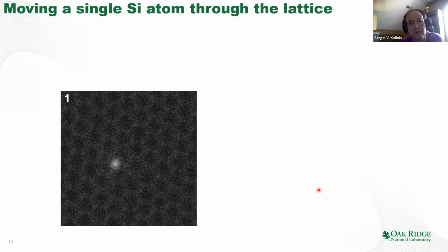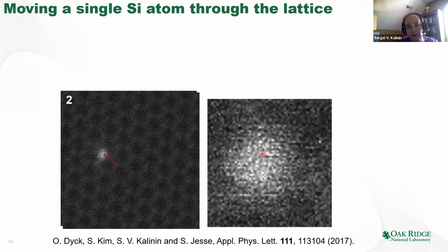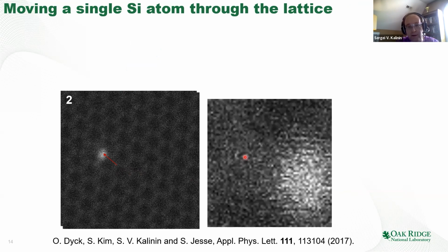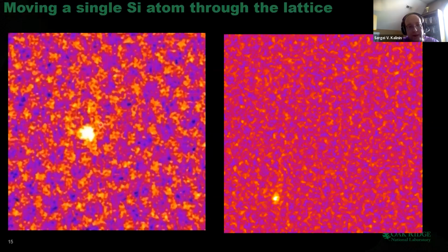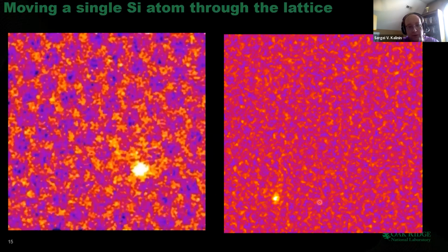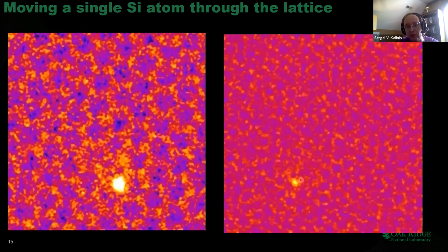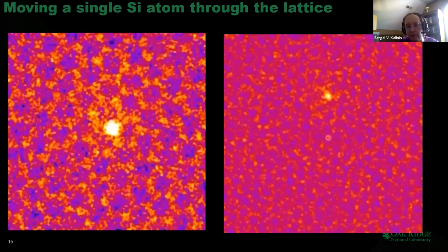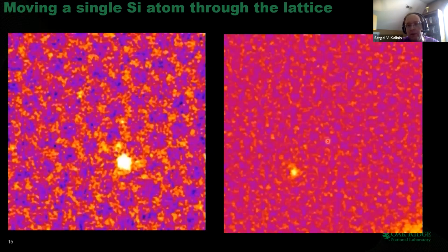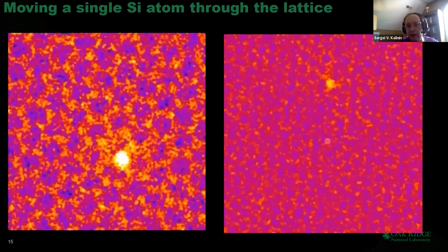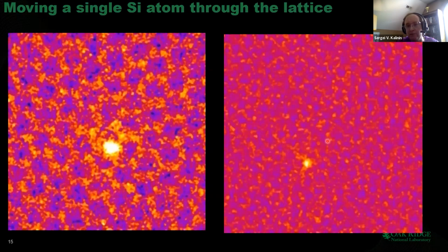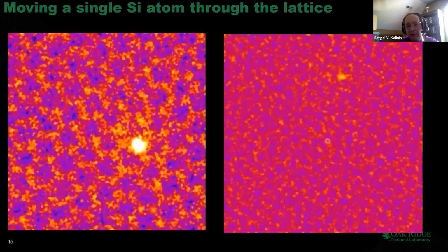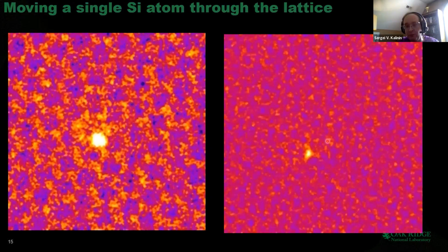It turns out that we don't even have to rely on a random process. The electron beam can be used to manipulate an atom and simply make it jump to the adjacent location. This is how it looks in the real experiment when the beam makes the atom jump. And if you're sufficiently patient, you can make the atom go in circles. You can make an atom go along a straight line, or at least a line which is straight for government work. The problem here is that this is done manually. It took a lot of time and a lot of attempts, because sometimes the atom is kicked out from the surface, sometimes the atom doesn't go where you want it to, but it is possible.